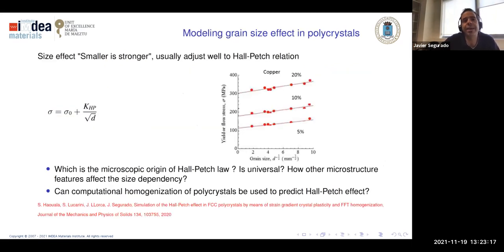Okay, so the first application is just to obtain stress-strain curves, but trying to reproduce something that we find in experiments. In experiments, we find a law that scales the strength of polycrystals with the size of the grain. This law is normally fitted to a Hall-Petch relation, okay, that follows this, and is that the strength is inversely proportional to the square root of the grain size. Okay, this law works pretty well, but it's pretty phenomenological. What is the origin? Is it universal? There are other microstructural features that depend on it, and the most important thing for us: can we use computational homogenization to predict this Hall-Petch effect?